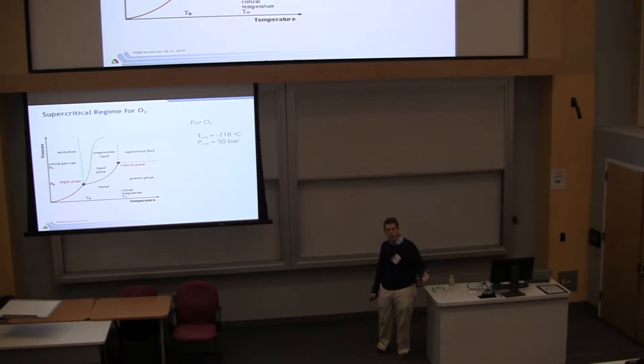Here's a table that shows lots of these. This is called an Ellingham diagram. And it's complicated. Don't worry about it. But all these lines are essentially thermodynamic measures of this equation for different metals and oxides. And they follow along and they tell you when, under what conditions of oxygen pressure and temperature, you're going to get a compound or you're going to get the elements. So you can look at these and read them off and figure it out.